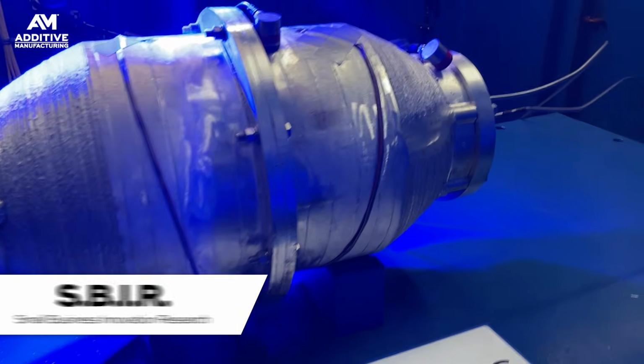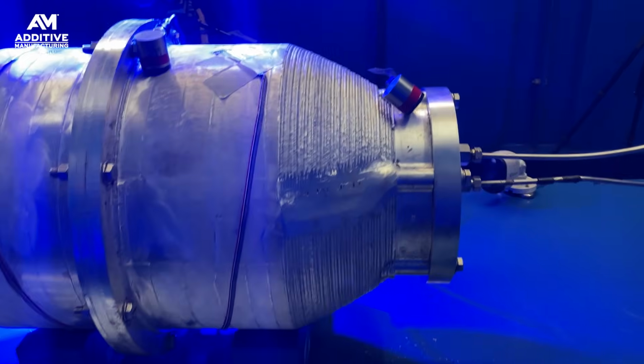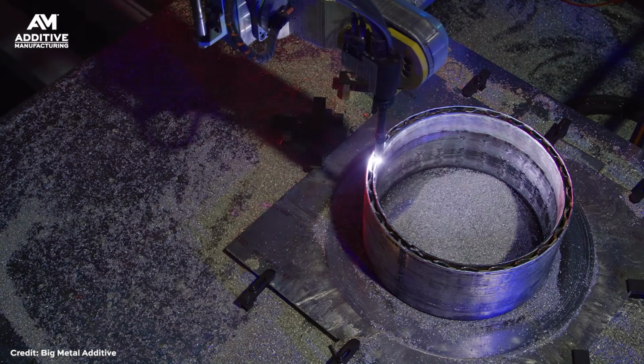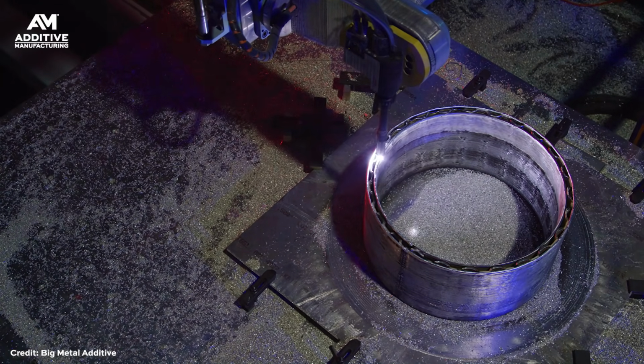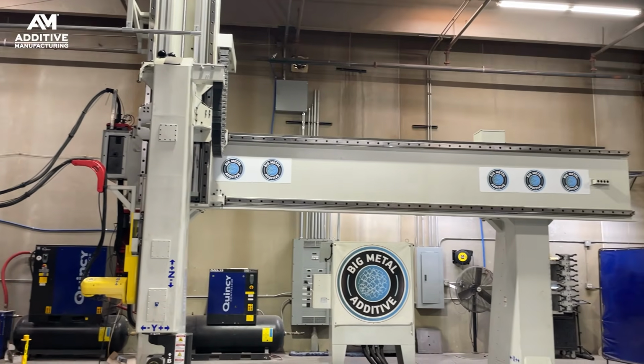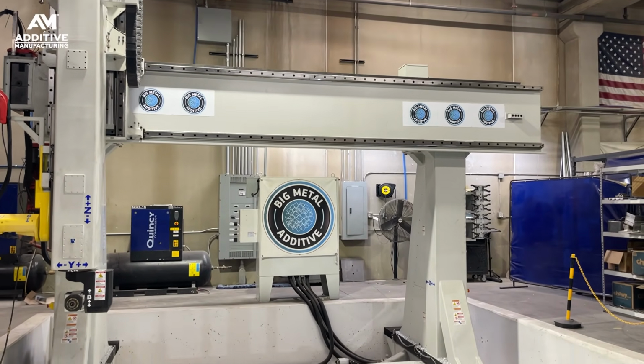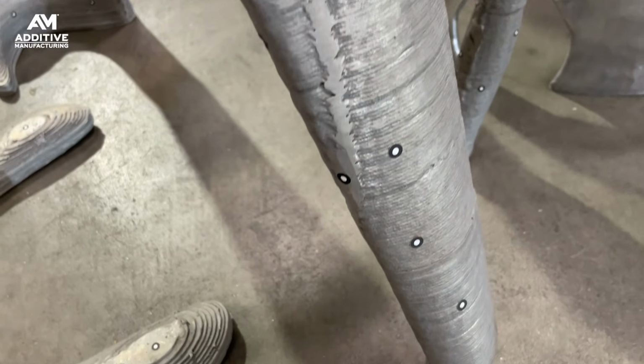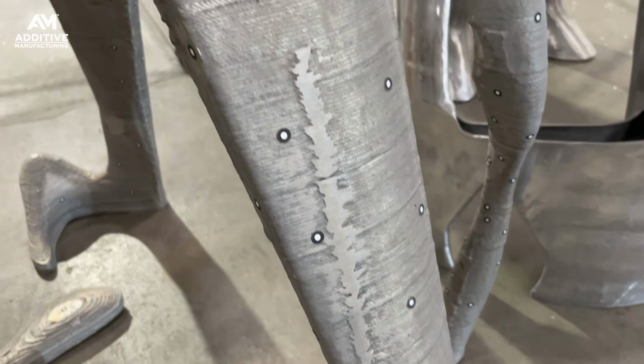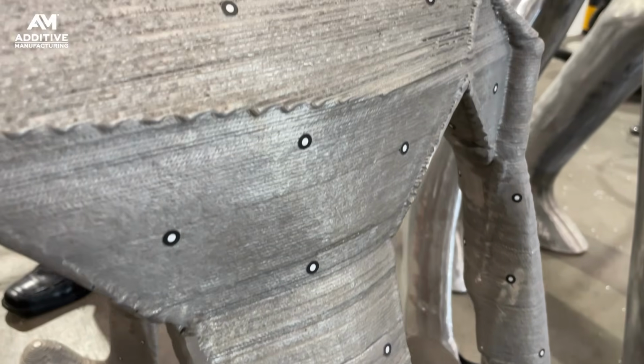We produced this part under a Navy Phase 2 SBIR. In this case, it was a pressure vessel for an unmanned underwater vehicle. And the pressure vessel is designed to contain all of the electronics while the vessel goes deep undersea. This pressure vessel that we tested was manufactured using wire arc DED, using our hybrid version. So we would start with a base plate, and then we would deposit the material on top of that base plate. We would machine the surface of every single layer of metal that we put down. That gives us a clean, flat, smooth surface for every metal deposition layer. It also defines the layer height.